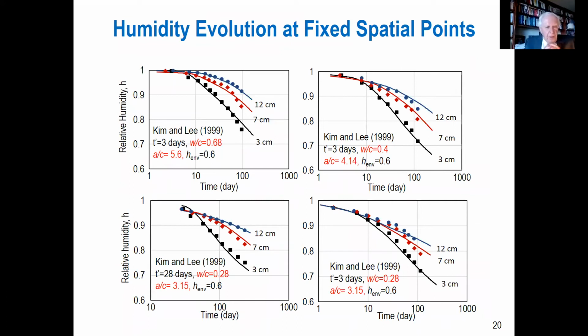Now it can be verified by plotting relative humidity versus time in a log scale. So what you have here is plots of relative humidity versus time for various fixed points in the specimen. So humidity gauges were placed at 12 centimeters deep below the surface, 7 centimeters, 3 centimeters, something here. For one water cement ratio, and as the water cement ratio changes, there is a significant difference. And this is everything for 60% humidity for different aggregate cement ratios. All this has to be included.